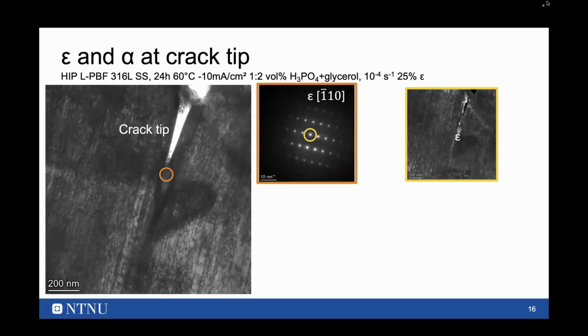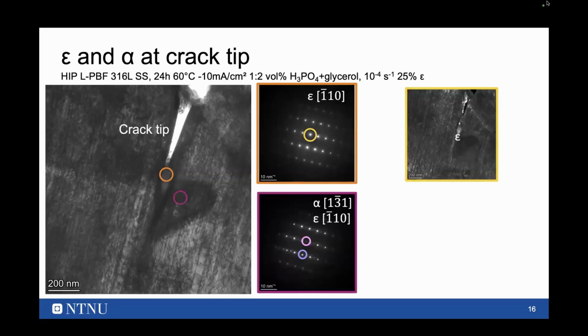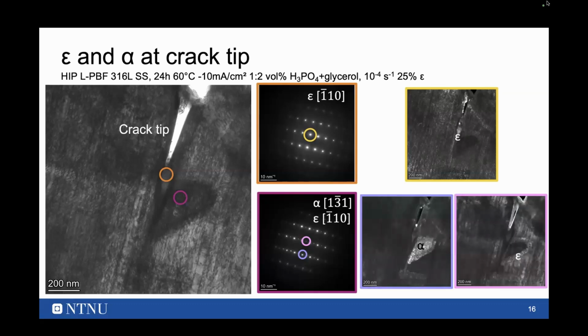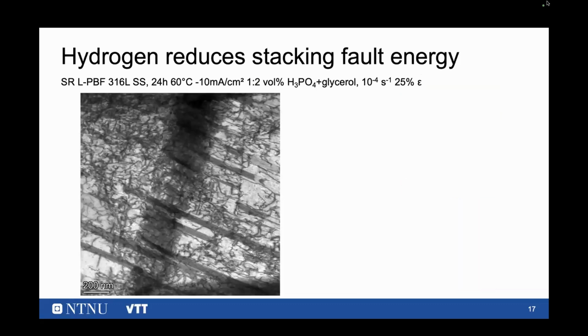Here we also see a specific feature, some kind of stress intensity field. We see a combination of both epsilon martensite and alpha martensite. Looking further into the dark field, the center is completely alpha, and around it we have some epsilon. So far, this was for the HIP condition.